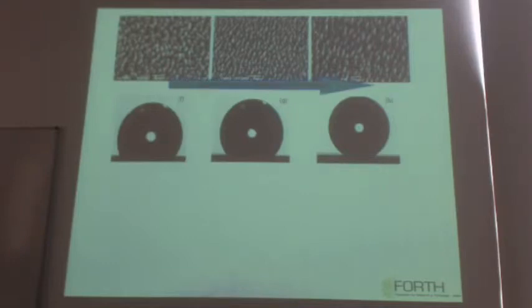So this is a series of laser structured surfaces in the low, medium, and high roughness. And as we increase the laser fluence, for example, the roughness increases, and here you can see that the wettability increases as well.